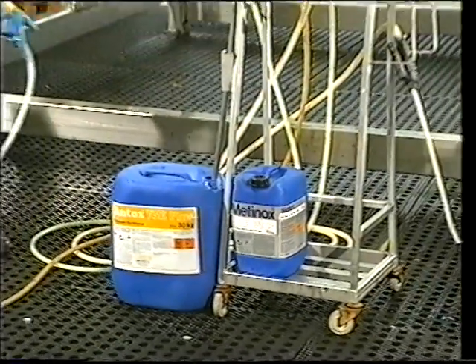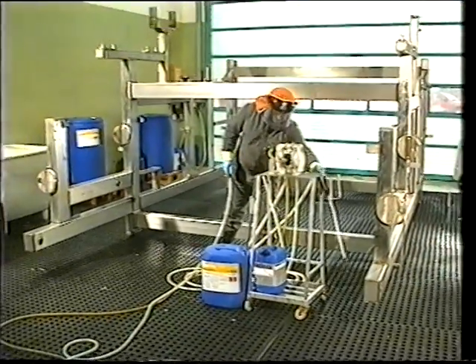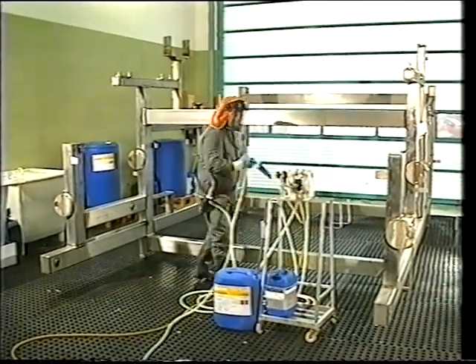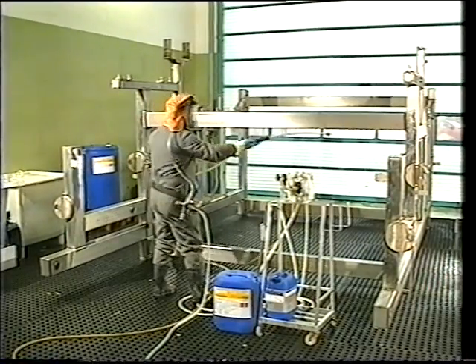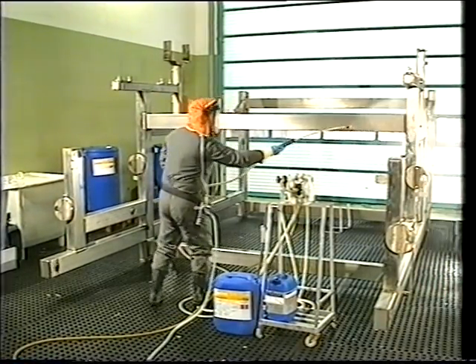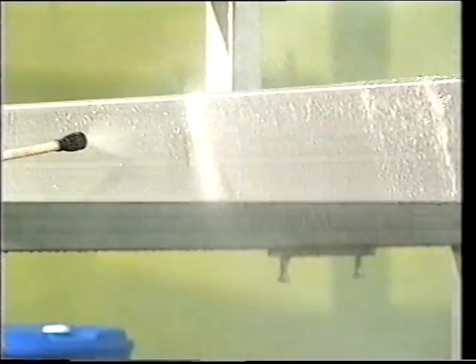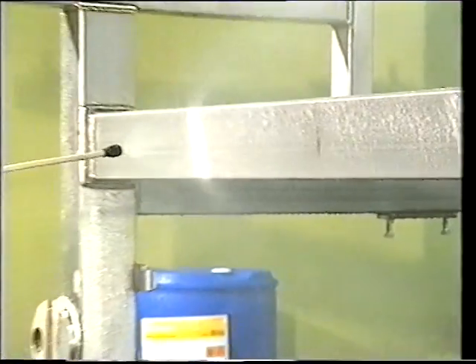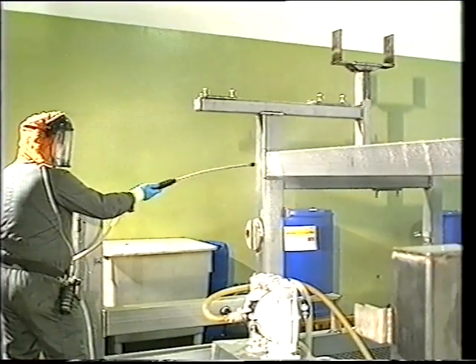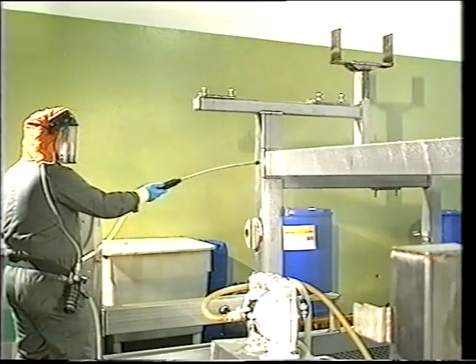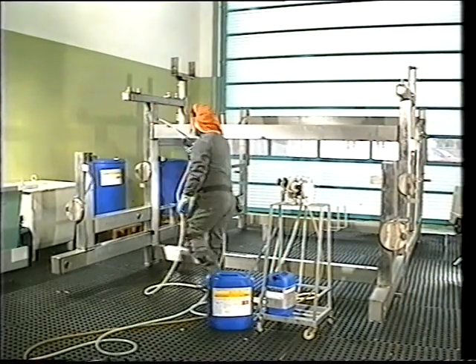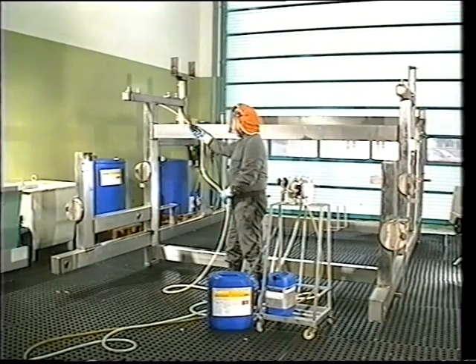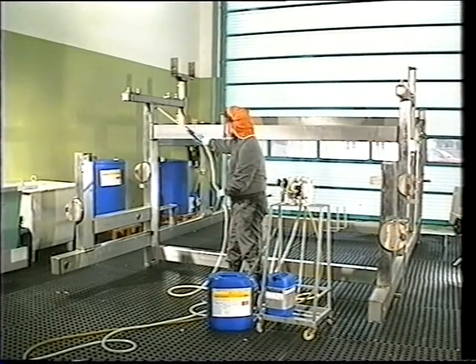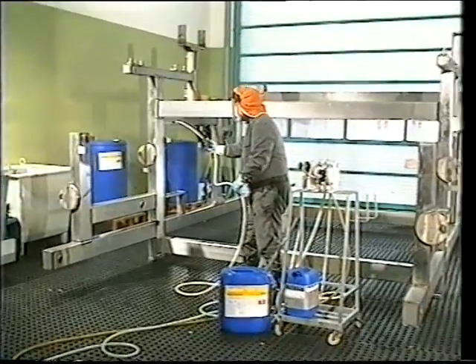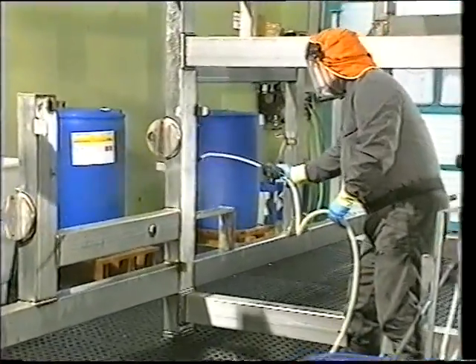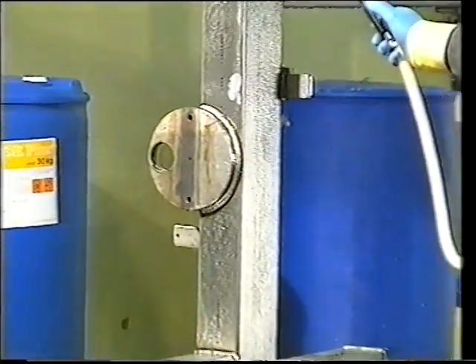Metinox 73E stainless steel spray pickle pickles both welds and surfaces in a single operation. It is sprayed onto the surface using a diaphragm pump driven by compressed air. Metinox 73E is a thixotropic pickling gel. Mechanical stress changes its viscosity. As a result, it adheres even to vertical surfaces and acts quickly and reliably. Scale and tarnish, dirt and foreign metals are all dissolved. Normally, the base metal is removed to a depth of less than 1 micrometer, but removal rates of about 5 micrometers can also be achieved if necessary.